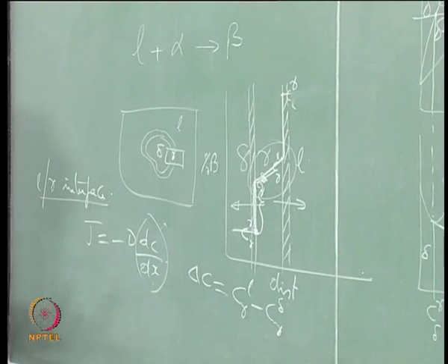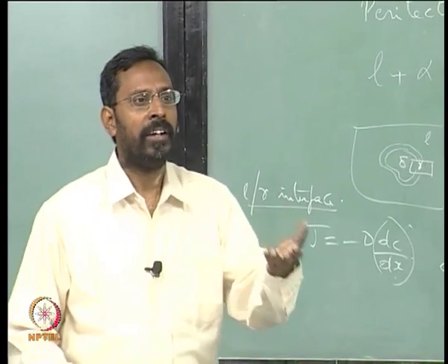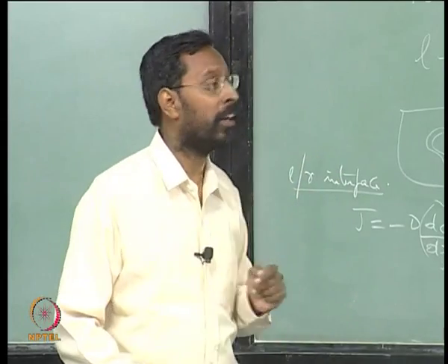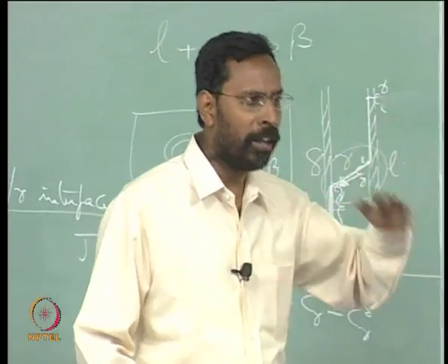So, there is absolutely no possibility of any peritectic reaction to occur at the peritectic temperature. You need to come below the peritectic temperature, and again the way we have talked in the case of eutectic, the lower the temperature that you come below the peritectic, the more this widens.